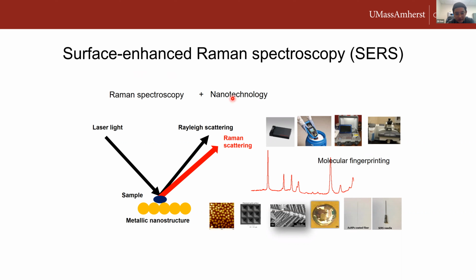In this case, as we can see, we have a little bit different setup than the previous technique. We introduce a layer of metallic nanostructure here. So the principle is the same. You will have Raman scattering generated when your compound is shot by the laser light. But here, when your compound is very close to the metallic nanostructure, these nanostructures will create what we call the hotspot. So this hotspot will greatly amplify the Raman signal, making this technique more sensitive. Sometimes we can detect your analyte down to ppb level.